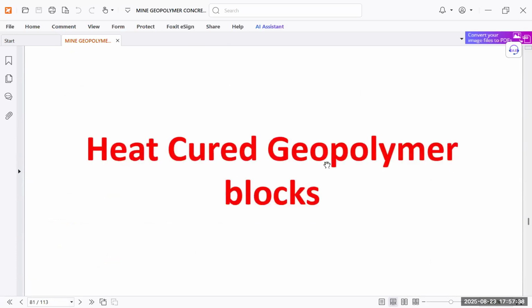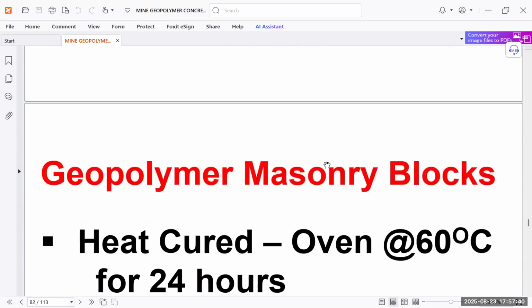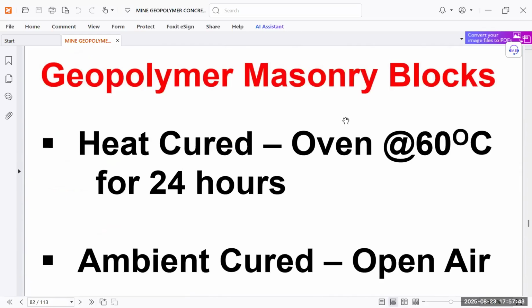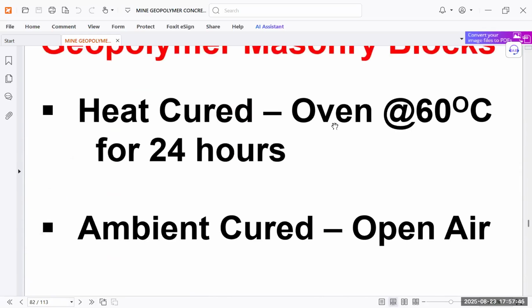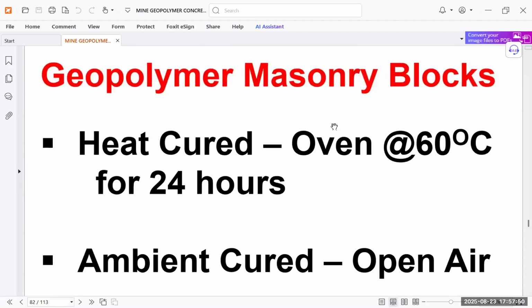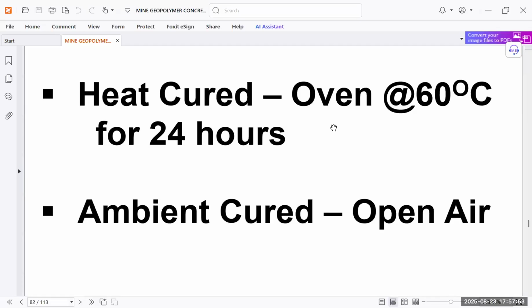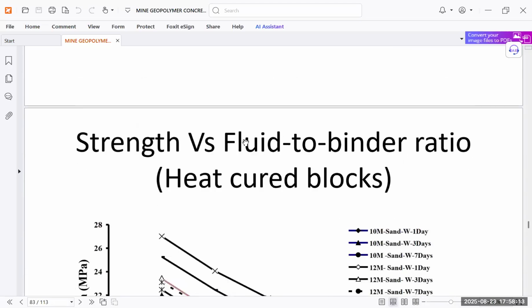Heat cured geopolymer blocks are also there. In this case, geopolymer blocks are either cured by ambient means, in open air, or we can also make them heat cured. The heat curing is done in an oven at 60 degrees Celsius for 24 hours. We put those blocks in for 24 hours at a temperature of 60 degrees Celsius, then it is heat cured. And ambient cured is open air. So those two types of curing are there in this case: ambient cure or oven cure, heat cured. The heat curing is done in an oven at 60 degrees Celsius for 24 hours.